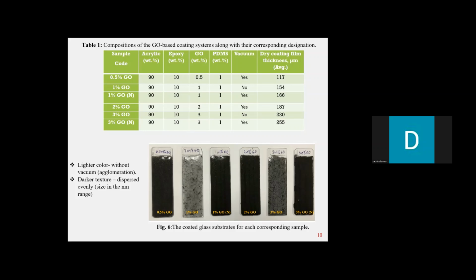How the coatings were applied on the glass substrate as well as on the metal substrates, I used the manual brushing method. When we are using two different types of resins, this is called a multifunctional coating. When we're talking about traditional coatings, it simply means a single resin only being used, for example, either just acrylic or just epoxy. When that happens, it will not produce a good barrier property for the coating. However, when we mix two separate resins, it gives us multifunctional features, and our coatings are also thick.